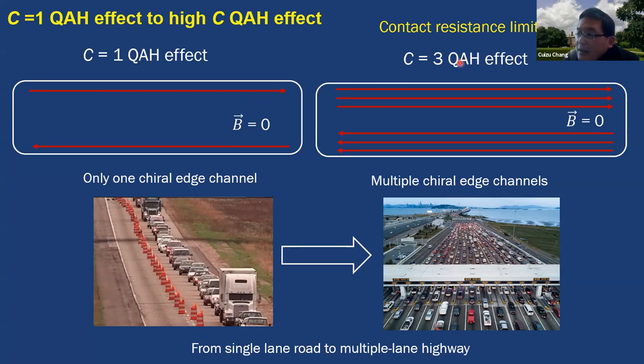But in this kind of high Chern number quantum anomalous Hall insulator, for example, this is a C equals three quantum anomalous Hall insulator, it can greatly reduce the time from the highway to the downtown. It's just like multiple lanes on the highway, so it will greatly reduce the time. And in the quantum anomalous Hall system, it will greatly reduce the contact resistance.